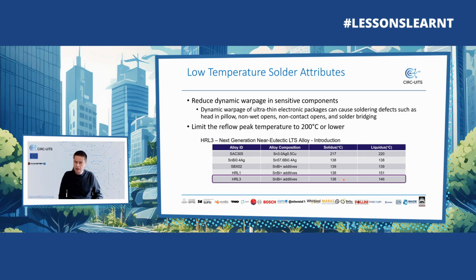Solidus of this alloy is 138, liquidus is 139 degrees C. For this typical one is 146. So that means you can reflow between 175 degrees and 200 degrees C. So you will reduce the reflow temperature below 200 degrees C, reducing the risk of non-wet opens and non-contacts and what have you.